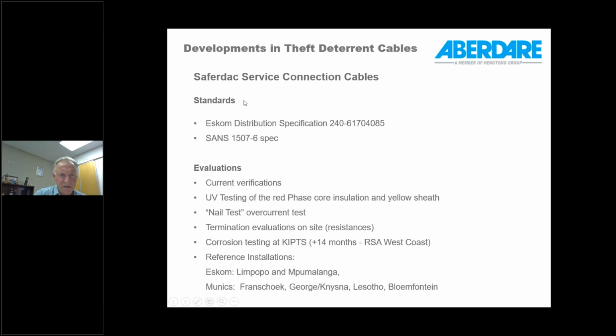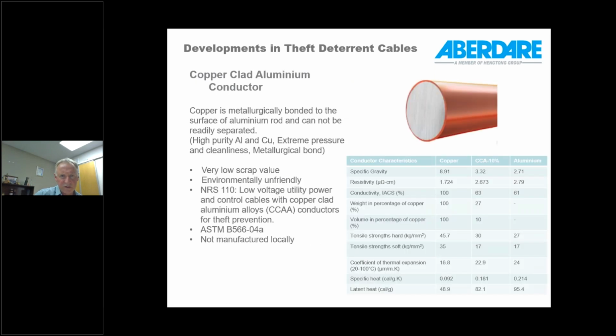The standards that are applicable is the Eskom distribution specification listed here, and also the SANS 1507 Part 6 specification, which had been amended. A number of evaluations had been done for current verification, UV testing, a nail test to test for short circuit overcurrent capability and burning of wires, creating an open circuit. Termination evaluations for resistance were done on site at the Eskom site. Corrosion testing was done, and there are now a number of reference installations for these kind of cables. So quite widespread at this stage.